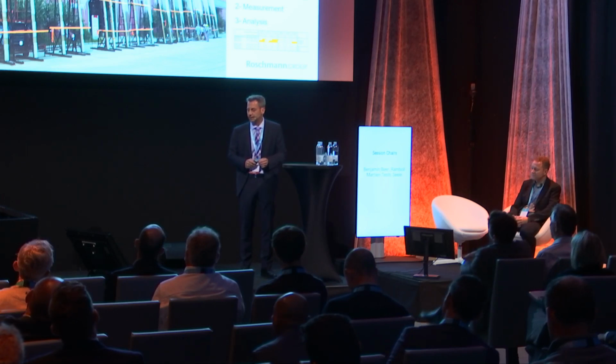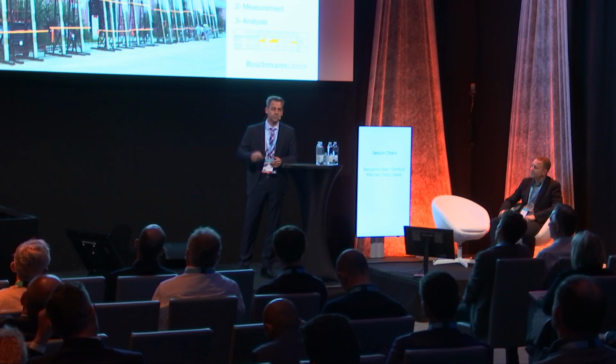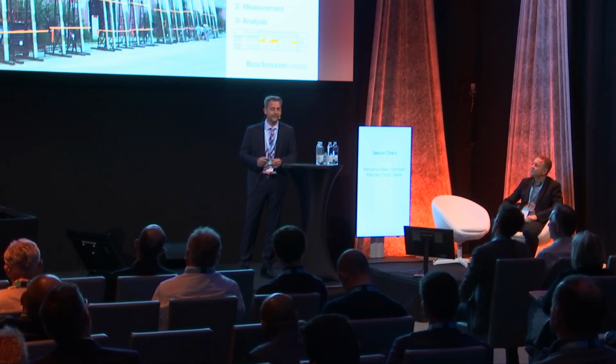So usually you are starting with making a corresponding visual mock-up, and this visual mock-up becomes the benchmark for your entire measurement. And then you go and measure over the surface at 3 points, at the bottom, center, and at the top, corresponding imperfections, which are in small increments next to each other. Creating this and putting that into a custom project individual standard based on that visual mock-up panel gives you a good alternate option of getting those corresponding roller waves under control. Again, we could have talked about that a bit more in detail if there would be more time, but that's an interesting practicable way of actually doing this and solving the problem the speaker before this presentation had.